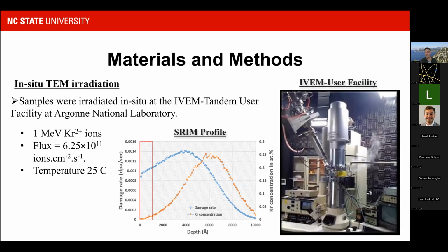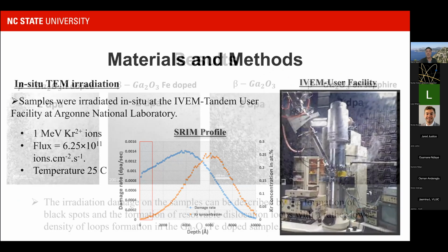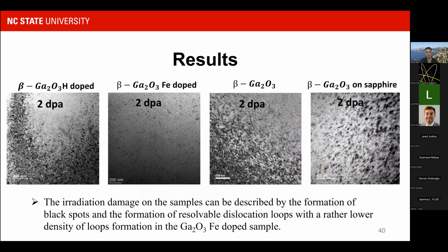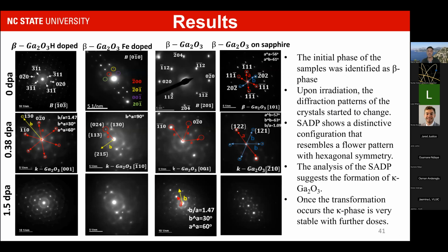We irradiated these samples in the same facility that I mentioned earlier. We can observe the damage accumulation and compare. In this case, we were comparing the 4 types of gallium oxide that we had. But we were more interested in the phase stability of it. And that is an aspect also that you can get from electron microscopy by looking at the diffraction patterns. And if you see here, regardless of the gallium oxide, how it was grown or whether it's doped or not, when we look at the initial pattern we had for each of the cases, we had a beta phase, which is the thermodynamically most stable phase.